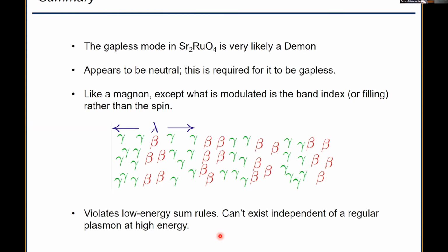But I think Harold's hit on a key point. I don't think demons are rare. They should occur in many different materials. So you might ask, well, why don't we see them all the time? The reason is because they don't couple to light. Light measures the long wavelength properties of a material. And a demon is neutral. It doesn't screen. It doesn't show up in epsilon of omega in the long wavelength limit. So you don't couple to it. Also, it sits at zero frequency in the long wavelength limit. So you need some finite wave vector probe that measures the charge response.